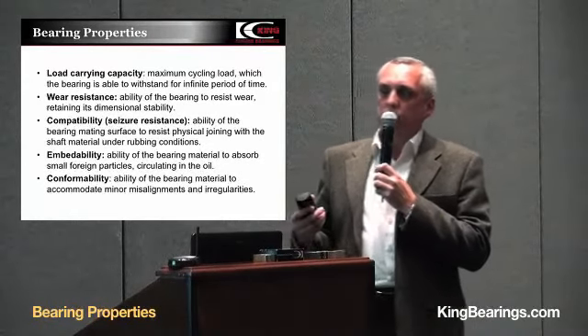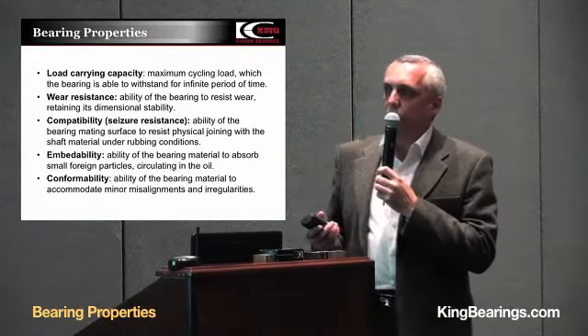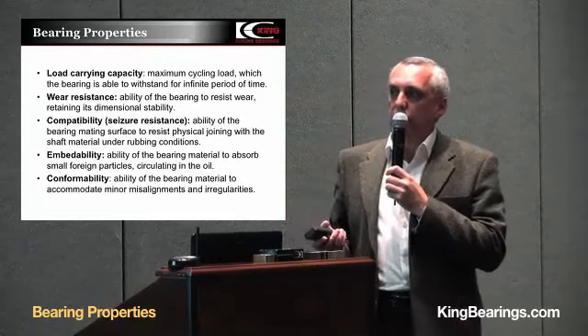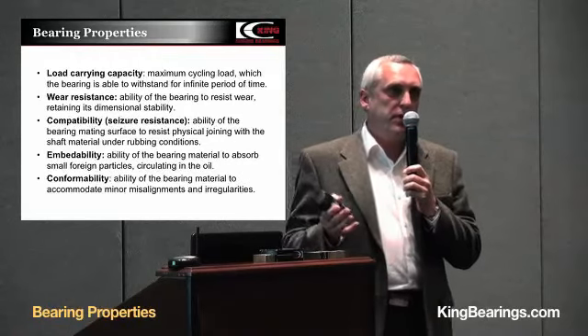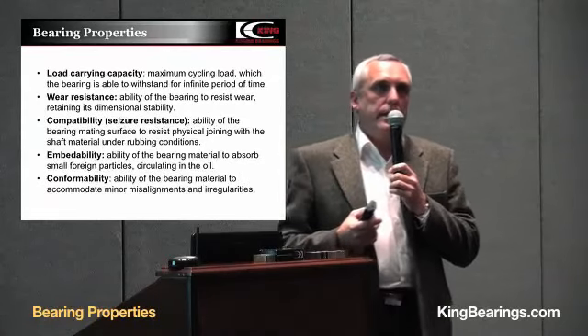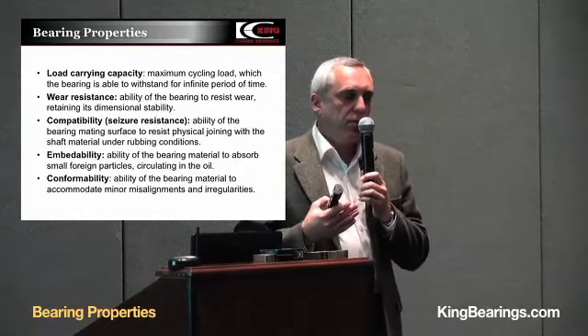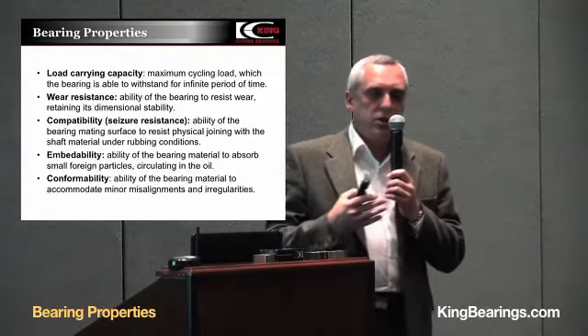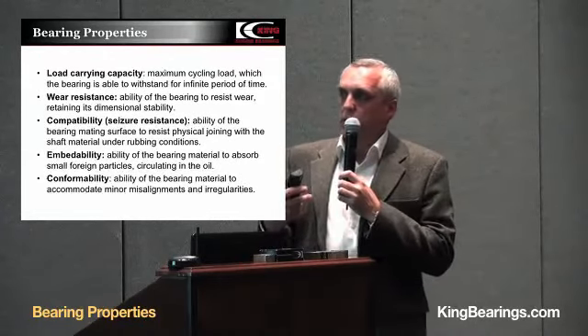Then embeddability. Embeddability is the ability of the bearing material to absorb small foreign particles circulating in oil. And the last: conformability. This is the ability of the bearing material to accommodate minor misalignments and irregularities. Nothing is ideal, nothing is perfect. The bearing and shaft materials may be non-parallel, or there may be defects in grinding of the journal surface — it may not be straight, maybe barrel shape or hourglass shape — and all these misalignments the bearing should accommodate.